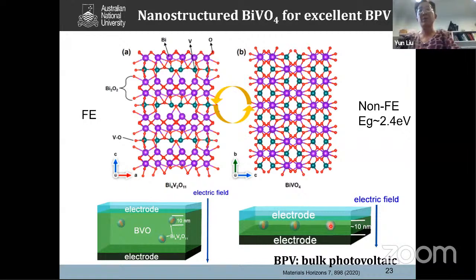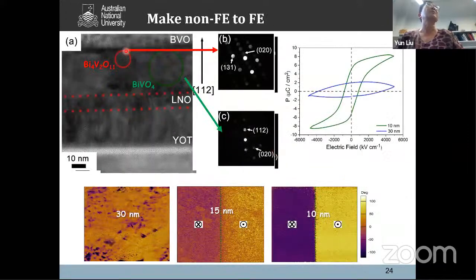So in that case, you can build very good nanostructure materials, and that enhances the photovoltaic effects. You can see here from the image, the height is less than 20 nanometers, and you get some regions as local chemical regions. And you can see here, if the thickness of the thin film is 30 nanometers, you don't have a good ferroelectric property. If you have 10 nanometers, your property is much better.